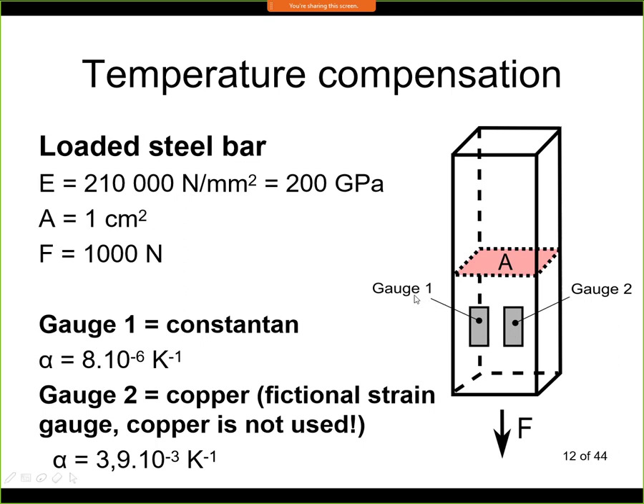The first strain gauge, gauge 1, is made from Constantan. Constantan has this temperature coefficient of resistance, and the second strain gauge is made from copper. Here I have to stress that this is a fictional strain gauge because copper is not used, and we will see soon the reason for that. Here you have the temperature coefficient of resistance, so you can see that compared to Constantan it's about 3 orders of magnitude larger. So if you have the same strain gauge made from Constantan and copper and the same temperature change, the copper will change its electrical resistance significantly.